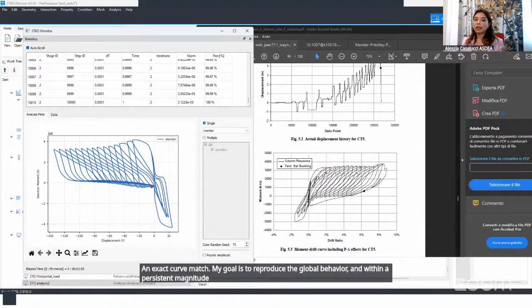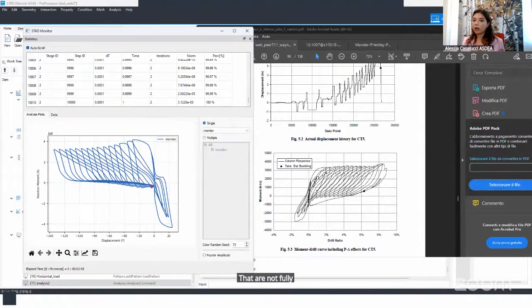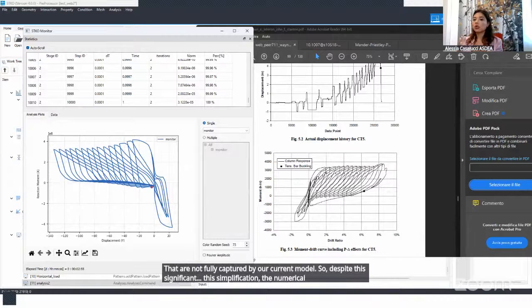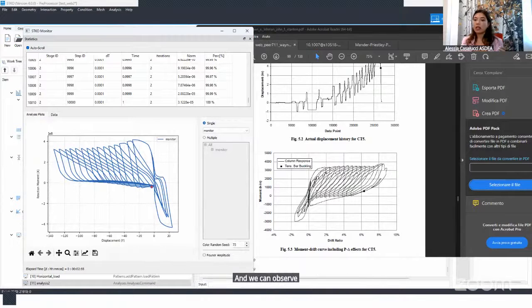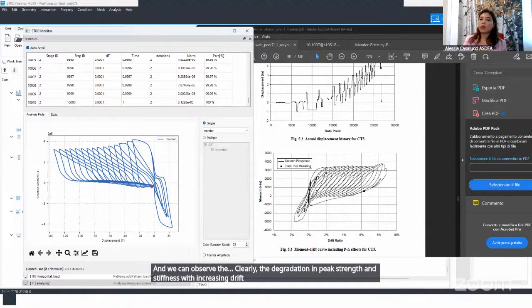In the experimental test, in fact, additional phenomena like bar buckling and Bauschinger effects had a significant influence on the response, especially in the post-peak range, that are not fully captured by our current model. So despite this simplification, the numerical results show a reasonably good agreement, and we can clearly observe the degradation in peak strength and stiffness with increasing drift cycle. These trends are consistent with the experimental behavior.